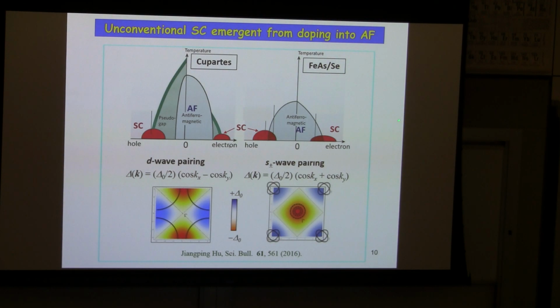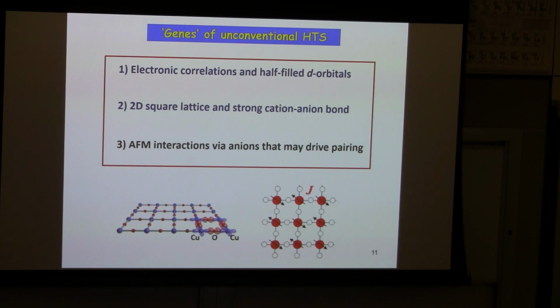In the same context, the iron-based material is basically S-wave, but it's S plus minus wave. S plus minus means that the superconducting order parameter changes sign between two different Fermi surfaces. If we use the convention that the unit cell contains 2 iron atoms, then the order parameter of S plus minus wave pairing can be expressed as cosine kx plus cosine ky. You can see that only the sign changes. In that sense, iron-based superconductors and the cuprate are like two sides of one coin. So there is really a similarity between the two systems. This is the starting point to search for the third family of high-Tc materials.